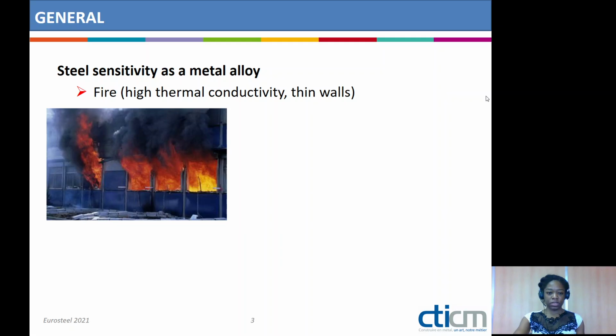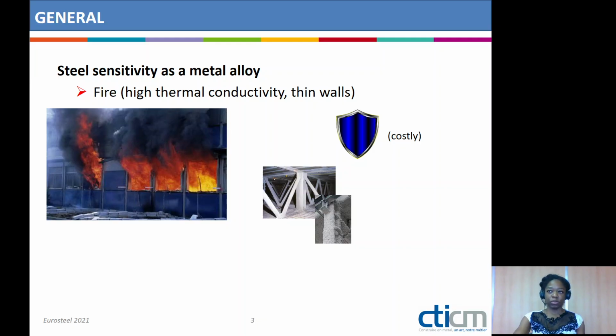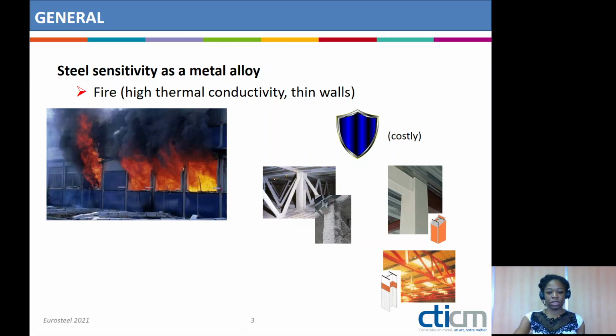Steel is also sensitive to fire exposure due to its high thermal conductivity and also to the fact that steel members are often made of thin walls, which leads to a quick rise of temperature when exposed to a fire. Again, solutions do exist to avoid or prevent this fire sensitivity, like spray protection, box protection, intumescent coating, or even concrete sometimes, which can be used in order to fill or to encase a steel member.